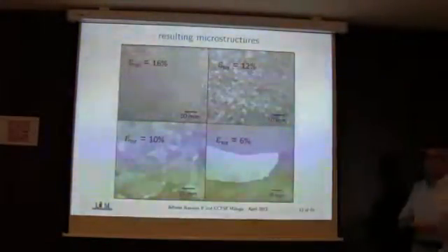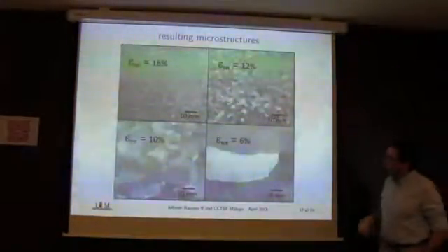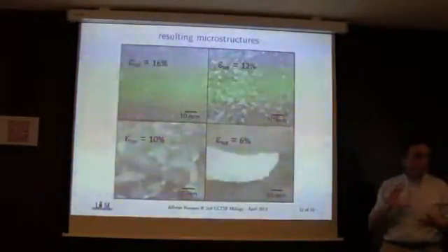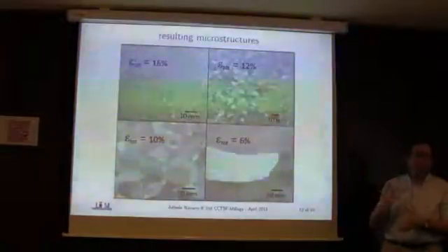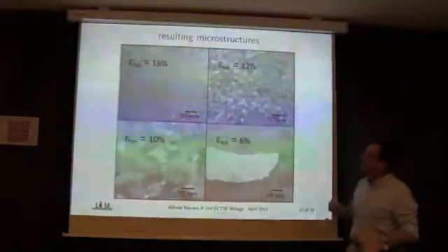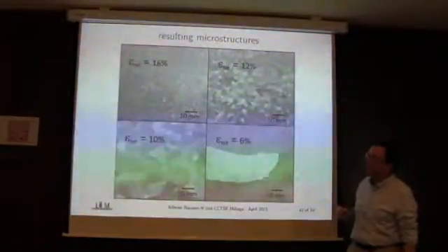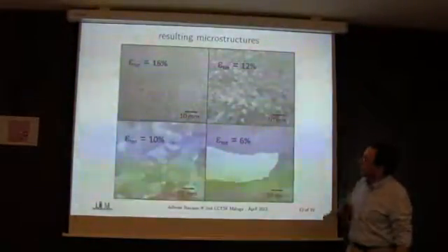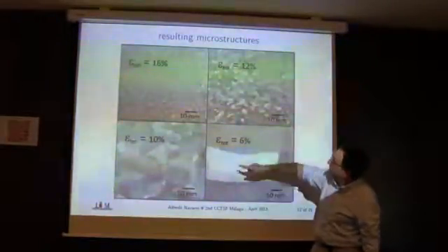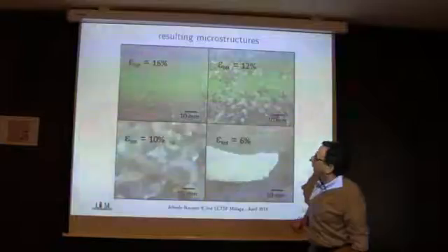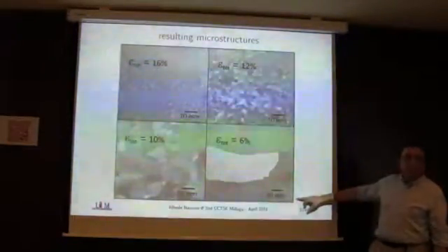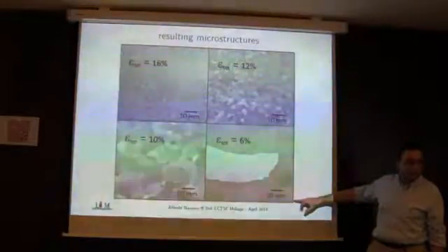This is the things that we actually obtain. The parameter that determines the final grain size that you will obtain is the intermediate thermomechanical treatment. So the level of deformation that you apply would result in a different size of the microstructure. You can see here that we have very small grains when we apply high plastic strain, and we can come up with these very big grains here, right?